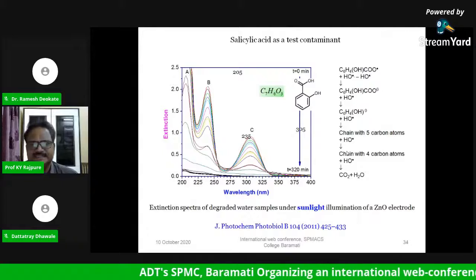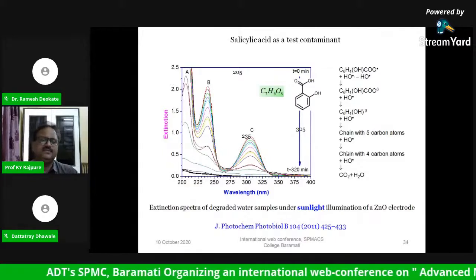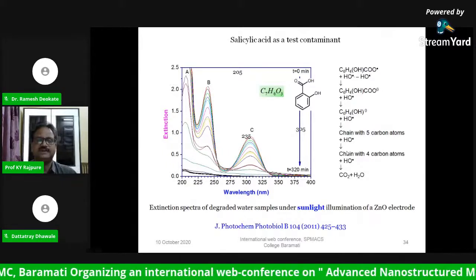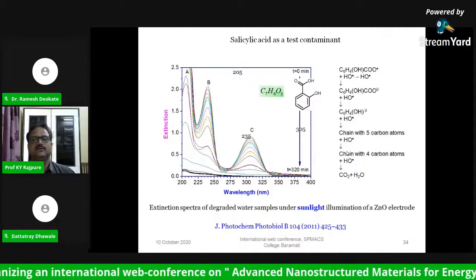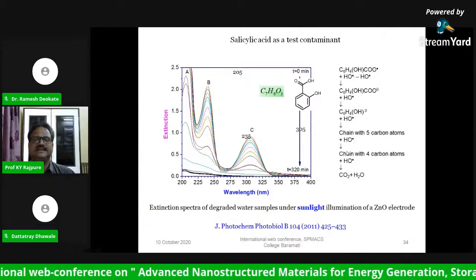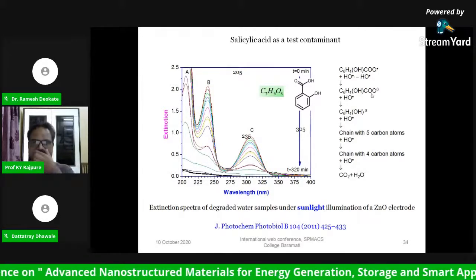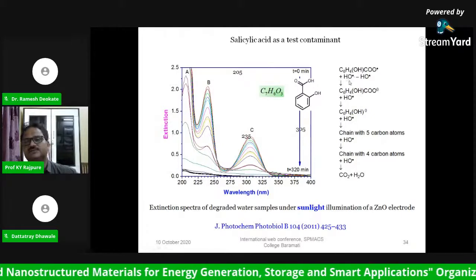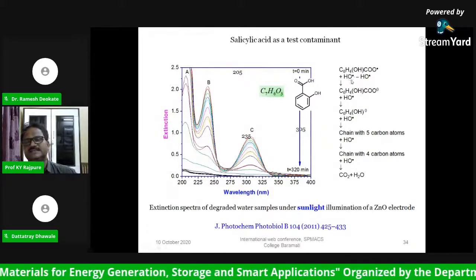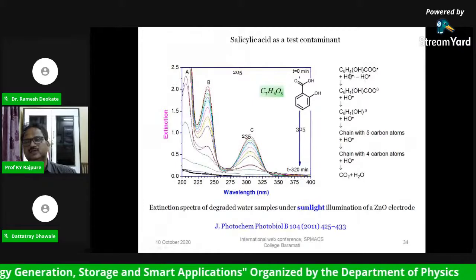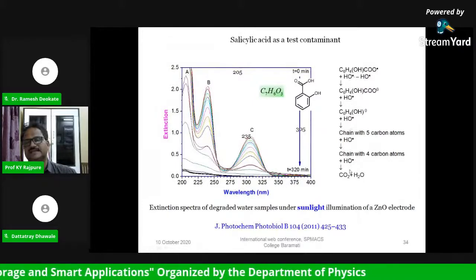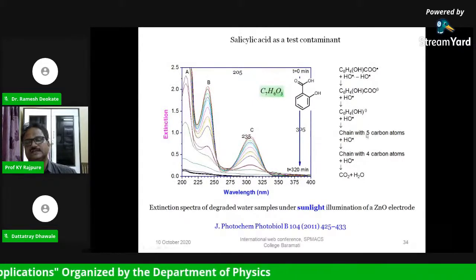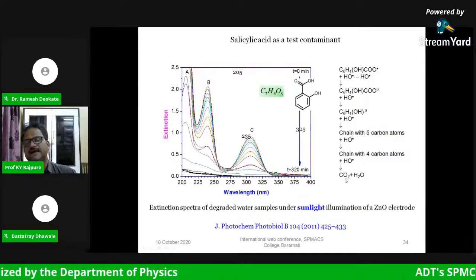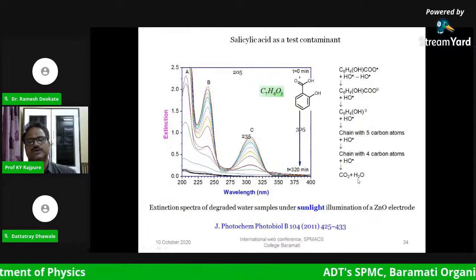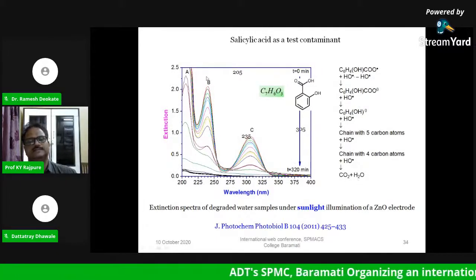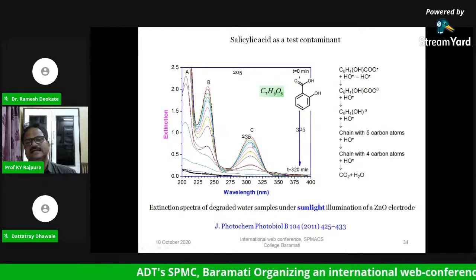And these are the results, as I said, where you measure the extinction, then the absorption spectrum. So these are the results on one of the test contaminants, salicylic acid. This salicylic acid, when it reacts with highly reactive species like OH dot, goes through various chain reactions, and it continuously loses carbons, and finally CO2 and H2O are produced, and the peak intensity continuously decreases.